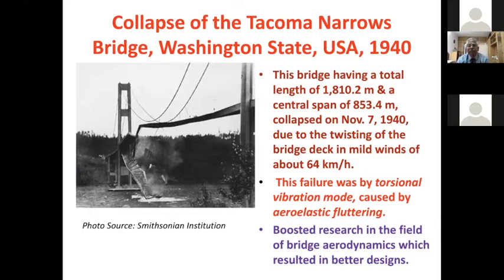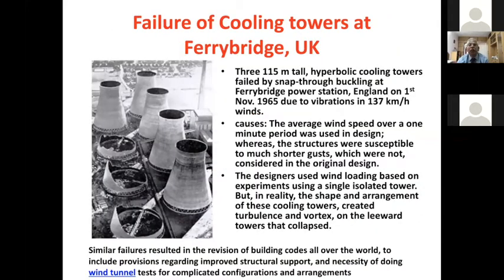This is another interesting failure, of cooling towers at Ferrybridge, UK. Three 115-meter tall hyperbolic cooling towers failed through snap-through buckling in England in 1965 due to vibrations in 137 kilometers per hour winds. The main cause was that the average wind speed over a 1 minute period was used in the design, whereas the structures were susceptible to much shorter gusts, which were not considered in the original design.